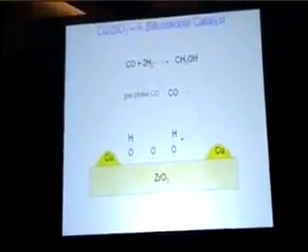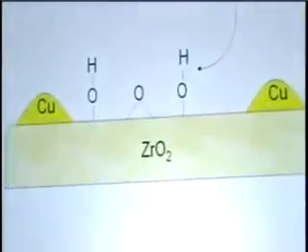So we started looking at this. And we did a series of in situ IR studies, both steady state and dynamic. We looked at CO adsorption, hydrogen adsorption, hydrogen spillover, and we concluded that in fact this catalyst is bifunctional, that both the copper and the zirconia have a function in catalysis. And let me show that to you by a series of cartoons. So here's the catalyst. It has hydroxyl groups, which you can see by infrared spectroscopy.